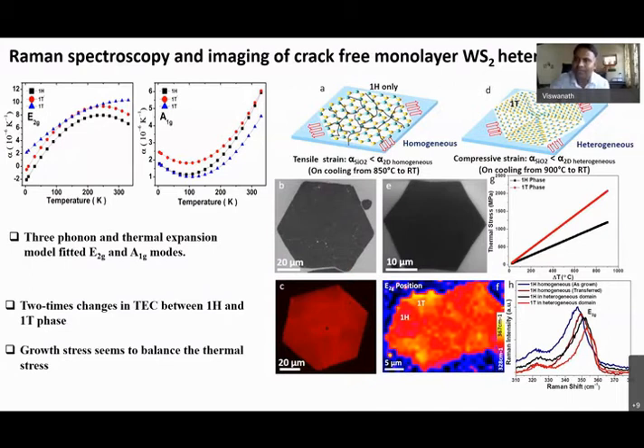But when you have coexisting phases, in this case 1H and 1T, two different allotropes, when they self-organize like this during the growth itself, they have some compressive strain built in. So this compressive strain probably somehow balances the tensile stress which is going to happen during the cooling when you do a growth at high temperature. So the heterostructures do not crack.